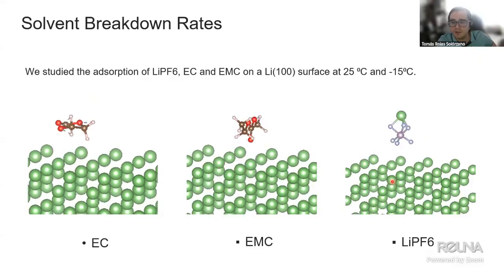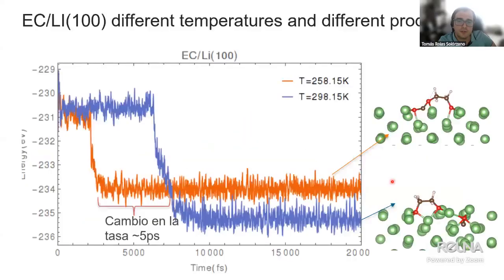An important first step is to know if those will break down or react with the surface at different rates, or any significant differences between 25 C and minus 15 C, which were the two temperatures that we were mostly interested in. What we see for the first result is that the EC does have a significant difference of about 5 picoseconds. It does produce very similar products at the end, but what we do is basically we simulate them at both temperatures and we see what comes out at the end. Both of them produce very similar products, but one of the temperatures, the minus 15 C, produces it slightly different, but much faster, about 5 picoseconds faster, which is a significant time in this type of systems.